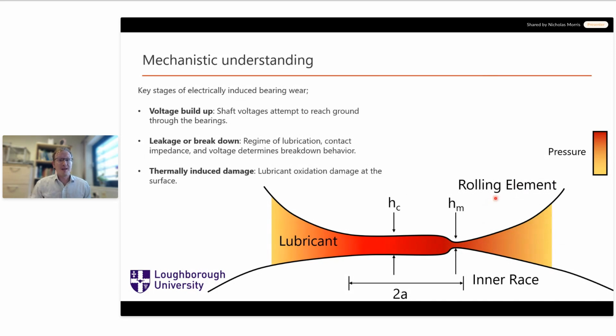So if we have the lubricant film there, it has a fairly low conductivity. And as a result, you'll see a small amount of current leaking across that interface when it's in the full film regime of lubrication, elastohydrodynamic. If the voltage is high enough, then the electrical field strength within the lubricant film will exceed the dielectric breakdown voltage of that fluid, and an electrical arc will form. And the electrical arc has a much lower resistance. So we have a low resistance electrical path formed between the 2 bodies, so inner race and rolling element, or rolling element and outer race.